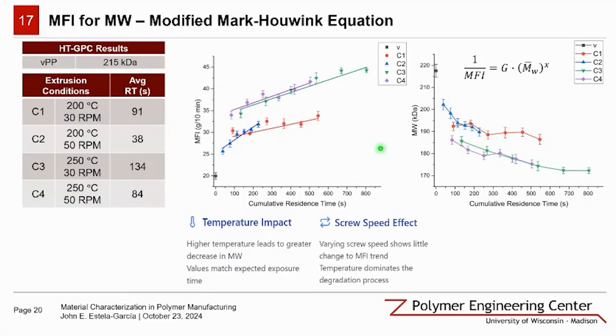So by understanding the relationship between processing conditions and polymer degradation, we can optimize recycling processes to maintain material properties over multiple use cycles. So this is essential for extending the lifespan of plastic materials. We've validated some of our MFI results by comparing them with gel permeation chromatography measurements of molecular weight.